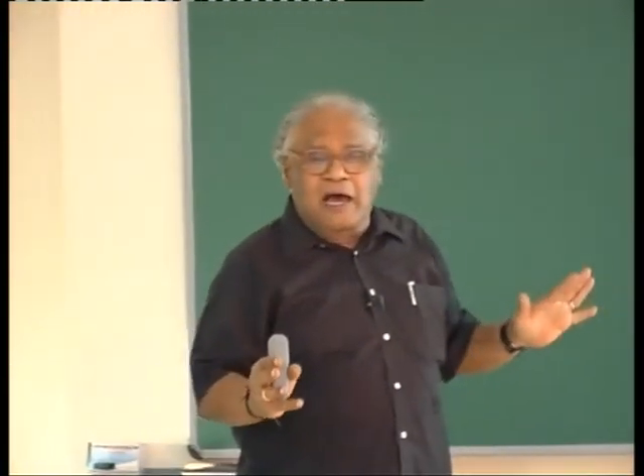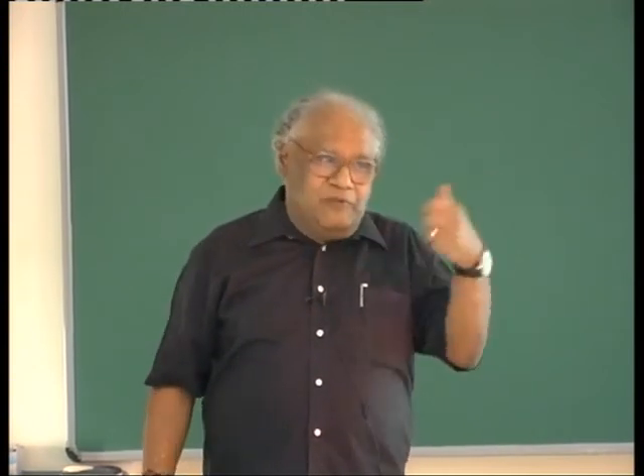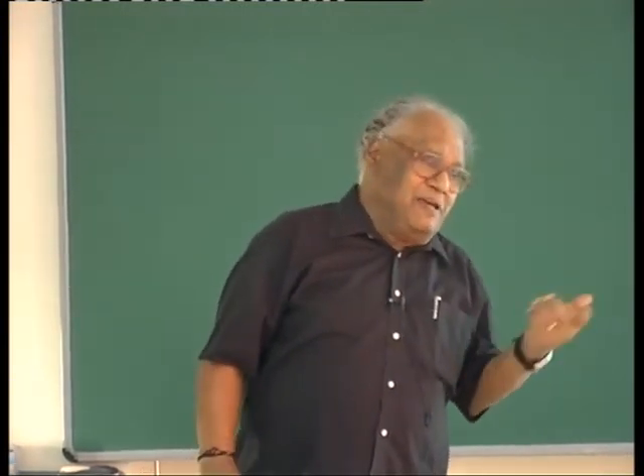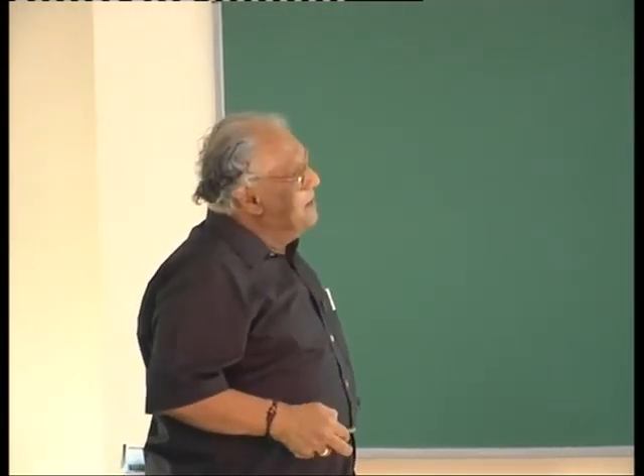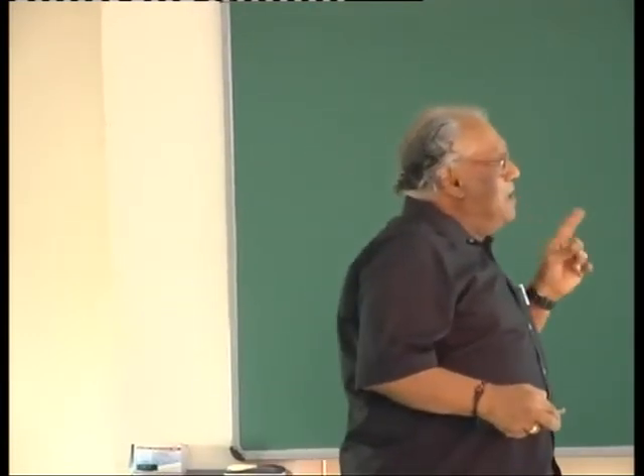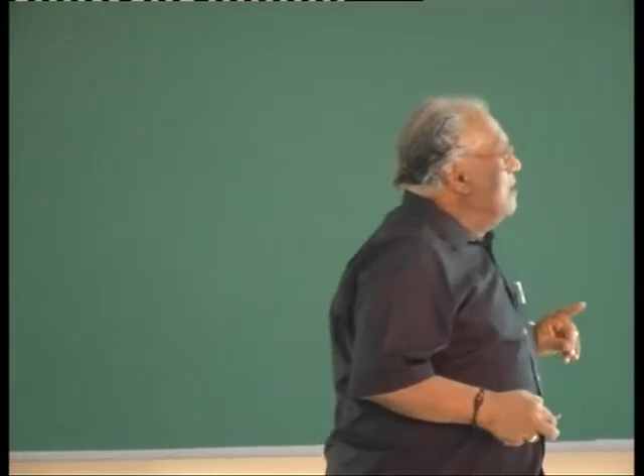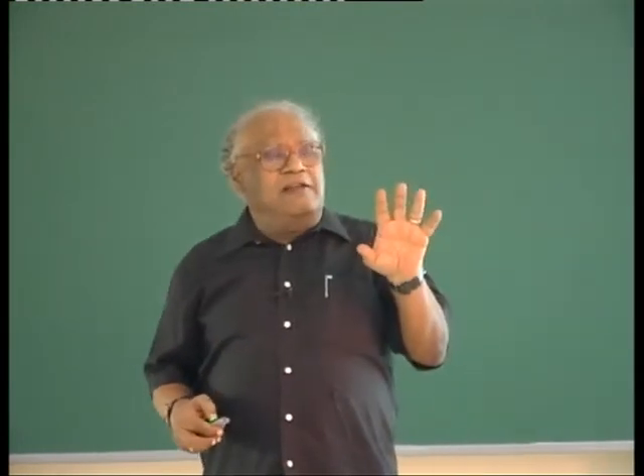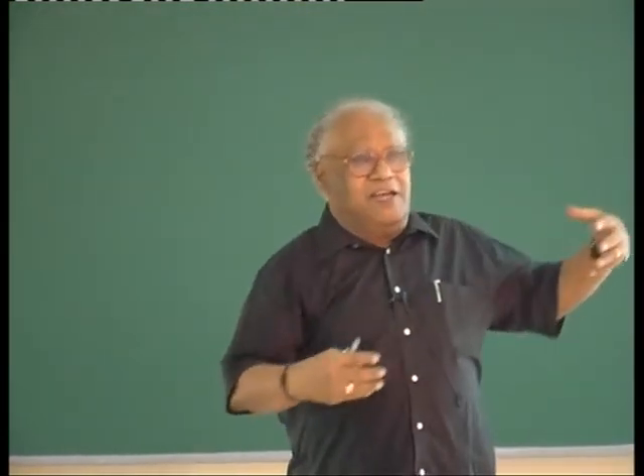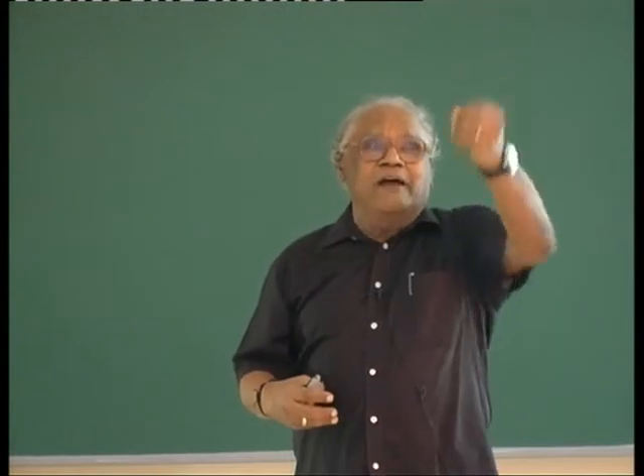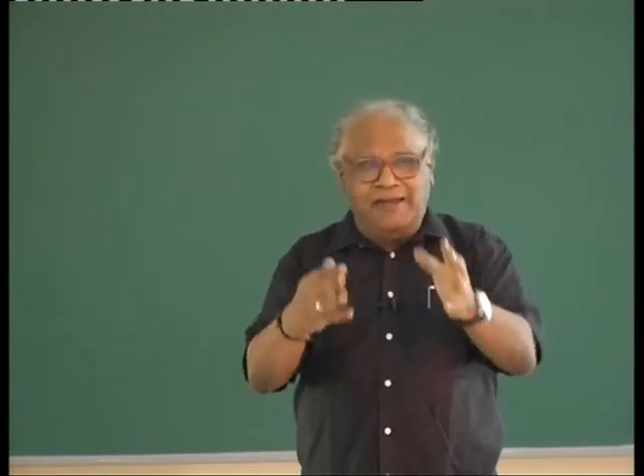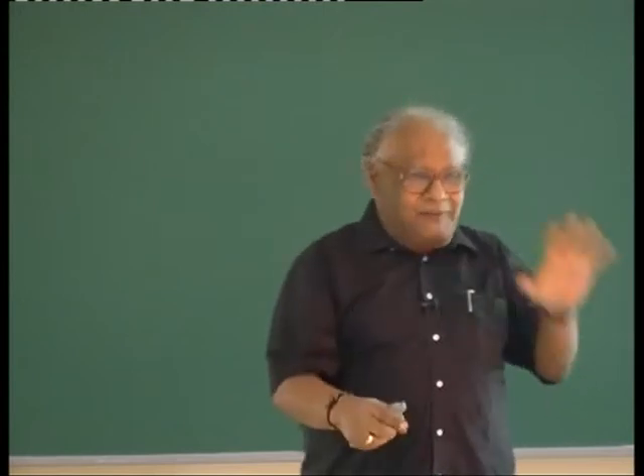So immediately we said, look, let us re-synthesize this material very carefully. Unfortunately, we can't do this work in India. So we sent students and my colleague, faculty, Dr. Sundaresh, to Japan to make these samples in NIMS and also in another laboratory in Tsukuba. We could make very good samples of bismuth manganite, where we had complete control of the oxygen stoichiometry. The reason this is important is that when we put in manganese oxide and bismuth oxide or carbonate, some carbon dioxide will always react with an oxide, and you get some carbonate. All such impurities are avoided.